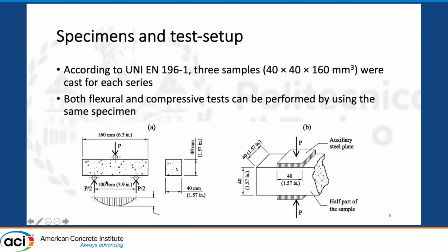with these specimens, we can perform both flexural and compressive tests. In particular, the first test is the bending test. After this bending test, we have a break in the specimen, and both the halves of the specimen can be tested in compression.